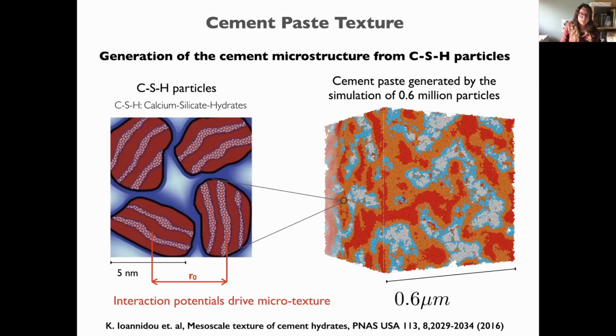We started from the hypothesis that we have these calcium silicate hydrates organized in a nanoscale particle, as we see here in the picture, which is around a few nanometers. The idea was to understand what are the interactions between these hydrates so that we can then produce a larger scale microstructure like we see on the right side.